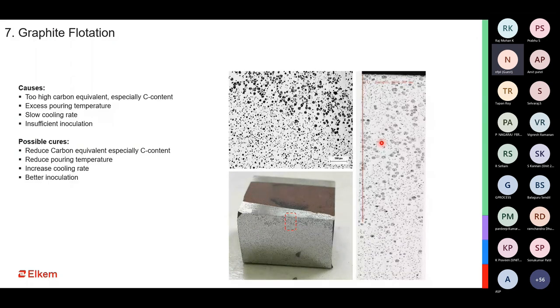So especially for a heavy section, when you have a higher carbon equivalent, you would get a very strong segregation of graphite towards the top, and that's why it's called flotation. It appears as if the carbon has floated towards the top, and this happens when you have a much higher carbon equivalent, a much higher pouring or tapping temperature, and a very slow solidification rate, which gives enough time for the carbon to float up.